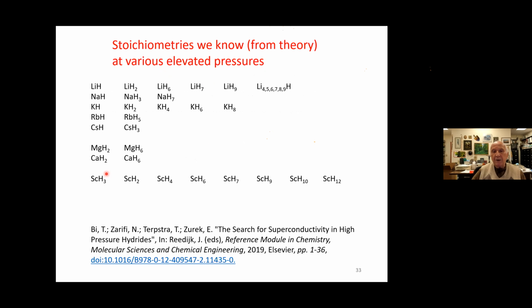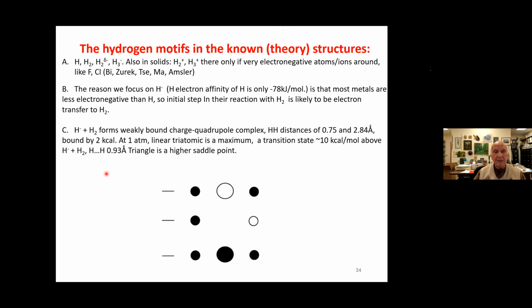Stoichiometries we know from theory at elevated pressures, and this comes from one of these reviews of Eva's, are varied. For lithium, they range from lithium rich as Li9H, to hydrogen rich. I already mentioned LiH to LiH6. And these are the things that I say we cannot predict. But what do we see in them? We see in these H2, maybe an H2 that's negatively charged. There's a construct. We do see H3-, a linear H3-, and we'll talk about that.